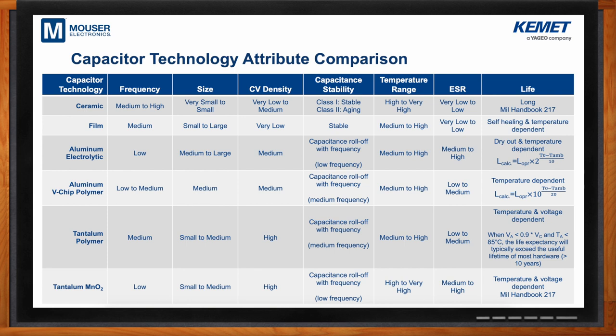So that's one advantage. And because the ESR is lower, the cap roll-off, which occurs in all electrolytics, will occur at a higher frequency. So instead of rolling off at 30 kilohertz or 50 kilohertz, you're now capable of going well up close to a megahertz before you start to see roll-off occurring for some part numbers. So that's the key benefit. And then the life is going to be much longer than what you see in a wet system. And the reason is because you don't have a dryout mechanism. It's a solid, dry system.